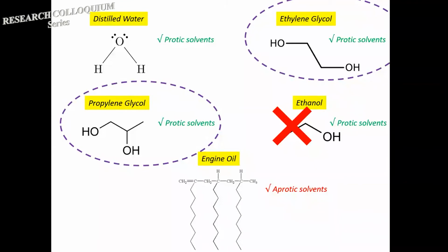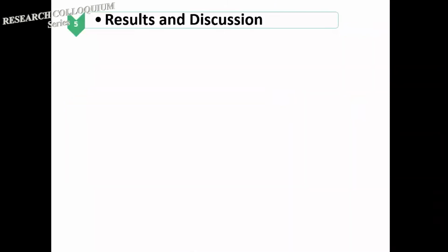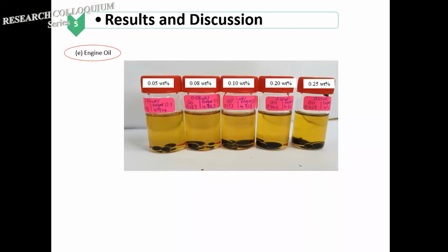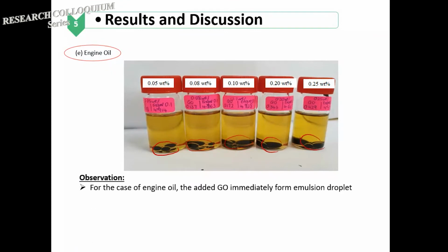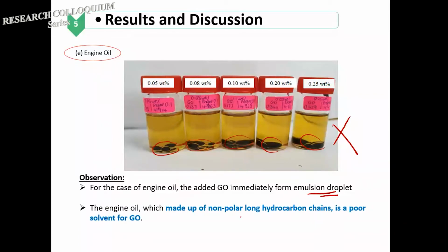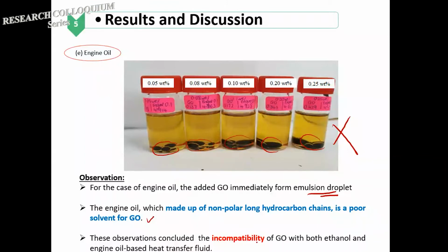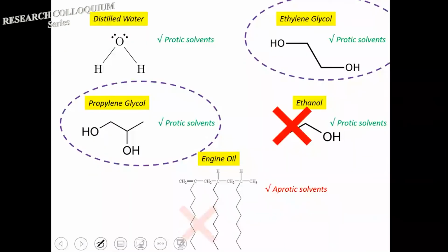Now, the last one, we try working on the engine oil. Since engine oil is a very common one that we use in automobiles, anything. Alright, so we try to put the graphene oxide into the engine oil. Now, this one, we found that the graphene oxide forms an emulsion or a droplet over here. Okay, a small droplet over here. For the case here, the added GO was found to immediately form emulsion droplets, so it also cannot be used. It is already forming droplets and settled down. The engine oil, made up of non-polar long hydrocarbon chains, is a poor solvent for graphene oxide. And in fact, we also know it's because the engine oil doesn't have any hydrogen bonding forming ability. So this observation concluded the incompatibility of the graphene oxide with both ethanol and engine oil-based heat transfer fluid. So again, this will be a no-no over here.